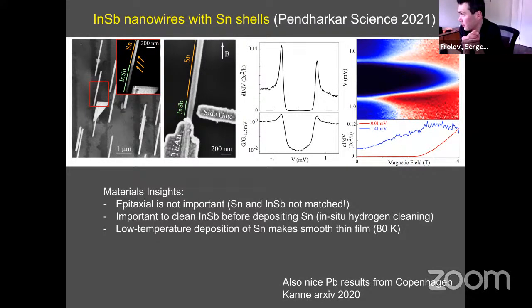Tin is, well, unexplored for such devices, underexplored, and it has some advantages. First of all, its energy scale, you know, moving the phase up, energy scale is better than aluminum, which was the best superconductor to work with until recently. So here in this plot in the middle, I show this energy scale. It's the superconducting gap. It looks pretty good. There is no states inside the gap. And it is about three times the gap of aluminum. So that's improving the energy scale, pushing it up maybe above one Kelvin, pushing it up in energy. It's also magnetic field resilient. It shows this parity conservation effect, which could come in handy if we want to make qubits out of this.